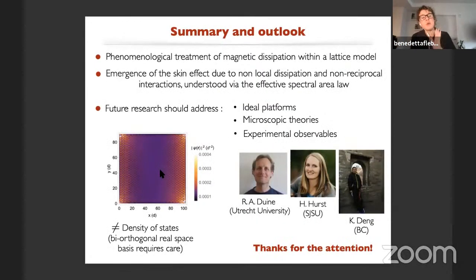So let me conclude with this. Here in general, we try to develop a phenomenological treatment of magnetic dissipation in a lattice model. It would be really interesting to try to develop microscopic theories that can reproduce a similar model. And we find, surprisingly, the emergence of the skin effect in a magnetic system, which in our case is due to the interference between non-local dissipation and non-reciprocal interactions. We can understand it via this effective spectral area law that we proposed, but I think this is a really first step. There are still many things to understand.